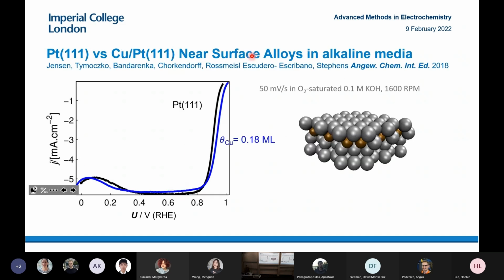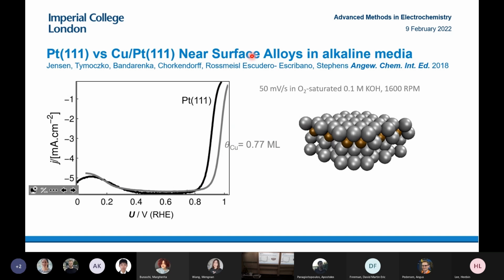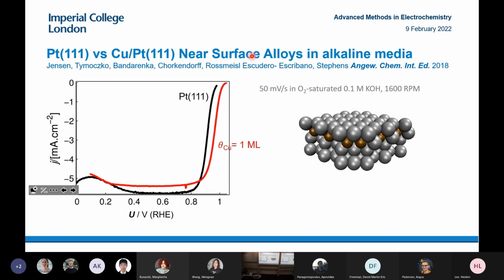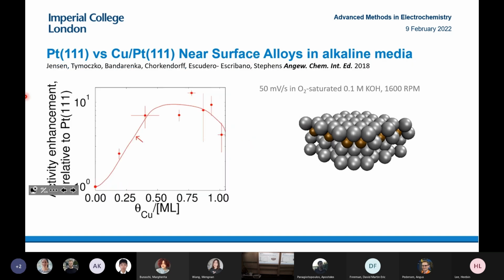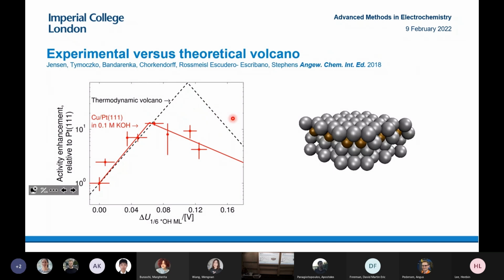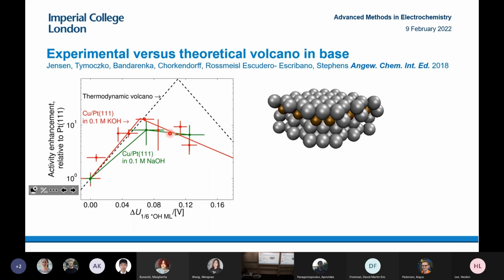And so we tested oxygen reduction in alkaline media. This is in potassium hydroxide. And what we found is actually just the same as in acid. When we put copper into the second surface layer, we see improvements in activity. The more copper we put, the more improvement, and then eventually if we put too much copper, it's slightly lower. So we can measure the activity as a function of copper deposit, and we see a shallow maximum here. We see similar improvements in activity, about 8 times improvement compared to what we saw in acid. So this is the result of the experiment. We also tried it in sodium hydroxide and saw something similar.